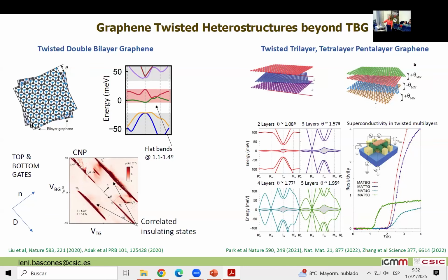in the sense that we can have here, let's say here, this is theta and minus theta, the trilayer. This is theta, minus theta, theta. And you can see here, if you go to 2 layers, 3 layers, 4 layers, 5 layers, we always find this alternating twist angle, and we always have flat bands. The band structure is a bit different, but we are always having flat bands. The angle at which they appear is a bit different. And in all these systems, up to the pentalayer, you can see here how the resistivity is going down. So there is this superconductivity associated really to this twisting process.